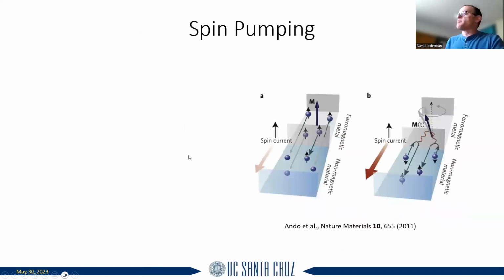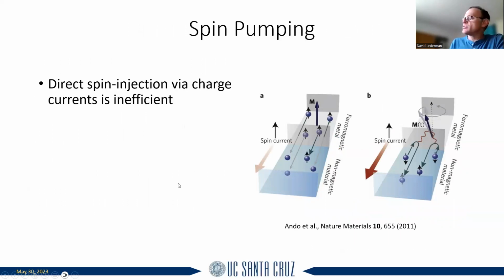And then there's the concept of spin pumping, which is another key issue that we need to talk about. What this does is it creates a direct spin injection via charge currents. Okay, but how do you do it? Well, you could think about taking a ferromagnet, like here on the left, and running a charge current. And then what happens is the magnetization will penetrate into the non-magnetic metal, but it's very inefficient. First of all, because it requires a charge current, so in terms of energy, it's inefficient. But also, the magnetization decays as it goes into the non-magnetic material, and so it has a finite length here, so it's inefficient.